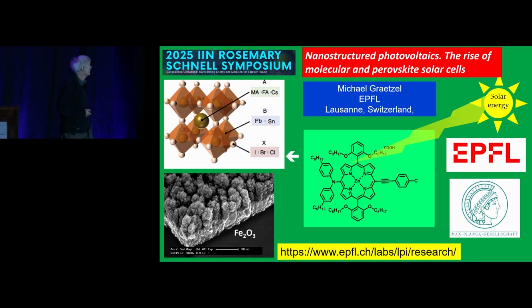So with that, the talk will be on nanostructured photovoltaics, and the title slide shows one example. It's iron oxide, rust. If you put light on rust, it does nothing. Fortunately, it doesn't do anything. However, if you nanostructure it, you will see the oxygen bubbles coming out. And why is that? The nanostructure design allows the positive carriers to escape to the surface before they recombine. They have a very short diffusion length in the nanostructure. But still, you absorb the light by using this cauliflower structure. So it's a very nice example of nanotechnology in energy conversion.